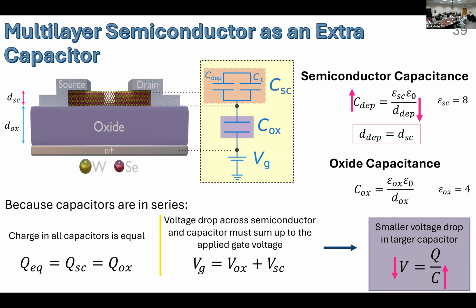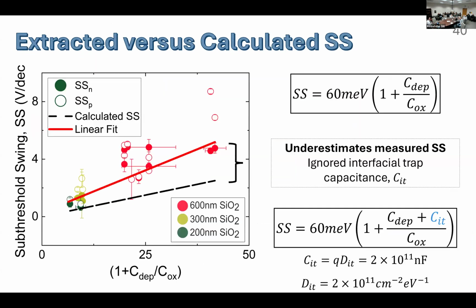So in order to verify whether this approximation of taking the semiconductor thickness to be the semiconductor depletion width holds, we extract the subthreshold swing of our devices and compare it to the calculated subthreshold swing using the equation that I presented earlier. The circles, either filled or unfilled, represent the extracted values, whereas the calculated fit is the one with the dashed lines. We see that the calculated subthreshold swing does not align well with our fit, and that is because we underestimated and neglected to include the interfacial trap capacitance.